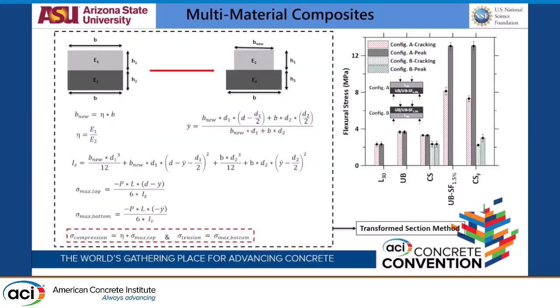Based on that, we used the transformed section method to see if the carrying capacity is an effect of print also, from which we saw that it's not exactly an effect of the mixture getting more strength or anything. It's basically a combined effect of these different moduli mixes acting together. We calculated the flexural stress at failure at the extreme fiber of the beam. We see that the strength is nearly similar to the mix that's in the extreme fiber. So if you have a UHPC SF 1.5% at the extreme fiber, the peak strength of the composite beam is also nearly similar to the homogeneous beam's strength.